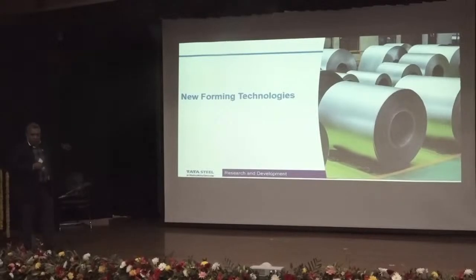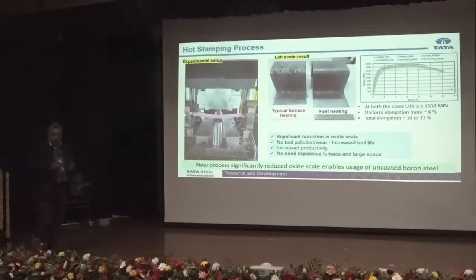Now, the third category of project where we are involved is new forming technology development. One of the forming processes already being used by the automotive industry is hot stamping. And here you have a boron steel, you heat the steel up to 900, 950 degrees centigrade, you quickly transfer it to the die, do the stamping, keep the die in the closed condition, and do the die quenching, and then the complete microstructure gets transformed into martensite, and therefore the strength you get in the final component is about 1400 to 1500 megapascal.